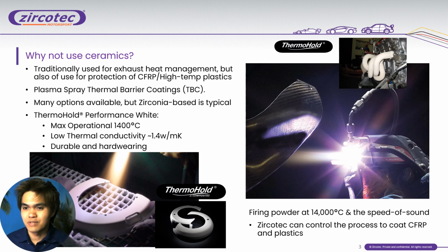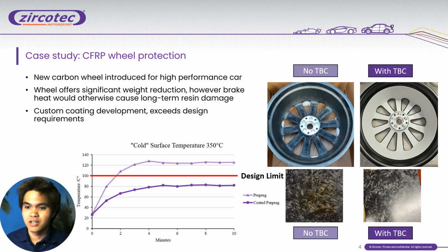To validate our claims, we have some internal testing via thermal and flammability tests. For our case study on the carbon fiber wheels, we took a simple carbon fiber plaque that was heat tested, exposed to a radiant heat of around 300 degrees. The plaque without the thermal barrier coating would go to around 130 degrees, which is above the design limit. But with the thermal barrier coating, we see that the carbon fiber is well below the design limit, protecting the carbon fiber resin and allowing it to be structurally sound.